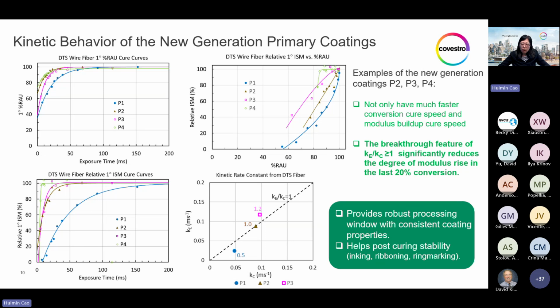And the primary coating at these processes will further increase, and in a lot of situations will even reach full cure, 100%. And the primary in situ modulus of the fiber in the final cable could very well already have jumped much higher, even doubled compared to the original bare fiber. And the new generation coating system has been proven to significantly reduce this modulus jump after the post-curing, and this is a great benefit to the final cable performance.